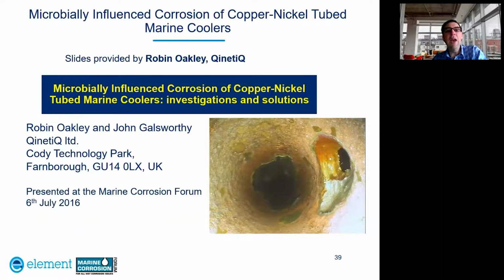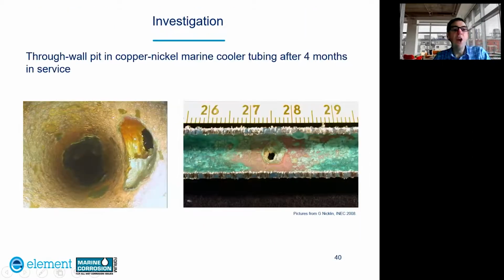So I just want to now move on to microbial influence corrosion and look at the corrosion of copper nickel tubed marine coolers. And these slides have been kindly provided by Robin Oakley of QinetiQ, and this presentation was made to the Marine Corrosion Forum in July of 2016. So the investigation found a through-wall pit in a copper nickel marine cooler tubing which had been in service for about 4 months.